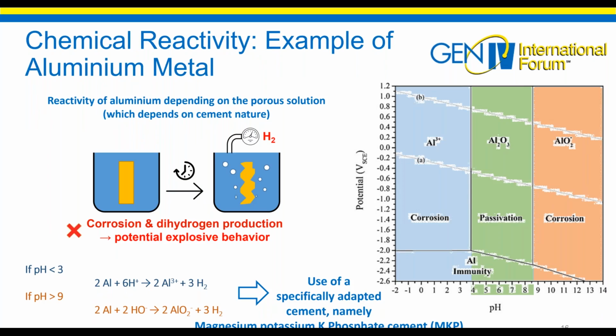The reactivity of aluminium metal depends on the pH of the porous solution of the cementitious matrices. Aluminium is reactive for pH values below 4 and above 9. In both cases, there is the production of dihydrogen. Between 4 and 9, we are in the passivation zone. This corresponds to the creation of a protective layer around the metallic aluminium. It is alumina. This layer protects the metallic aluminium from chemical aggression. It's like a barrier. The cement compatible with this pH zone is the phosphate cement.